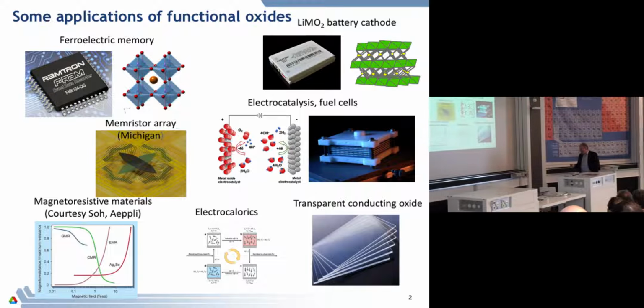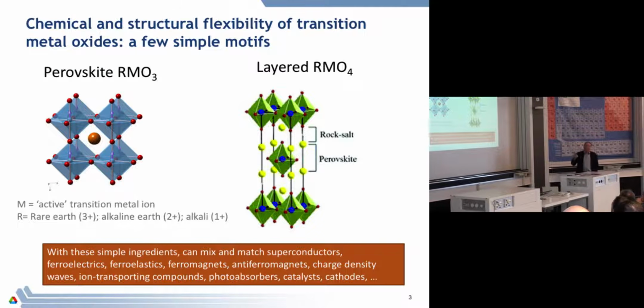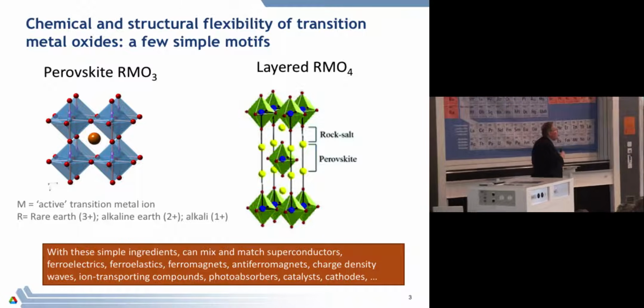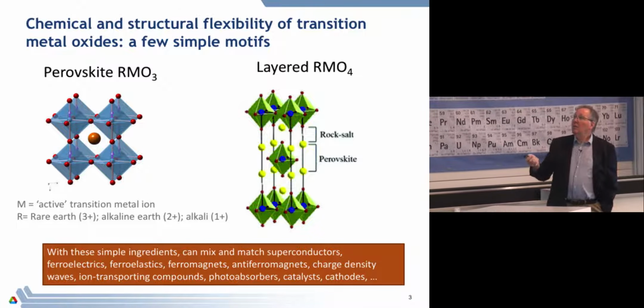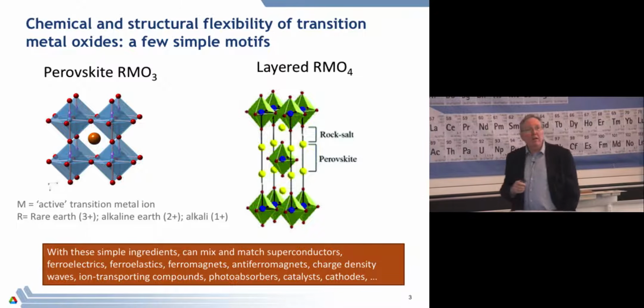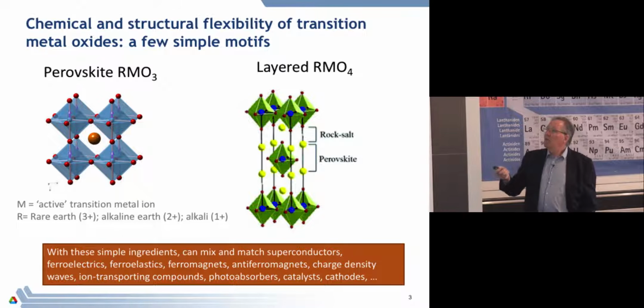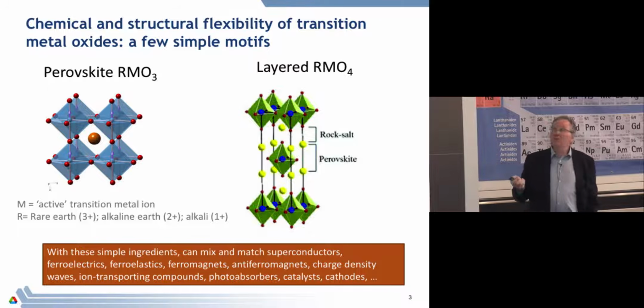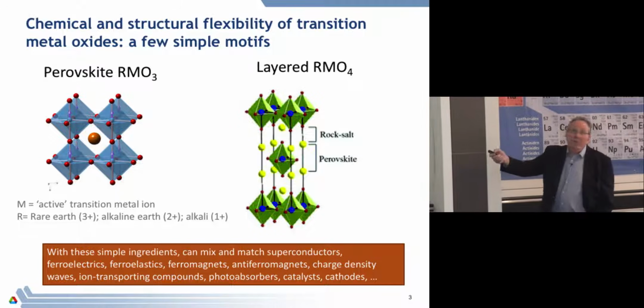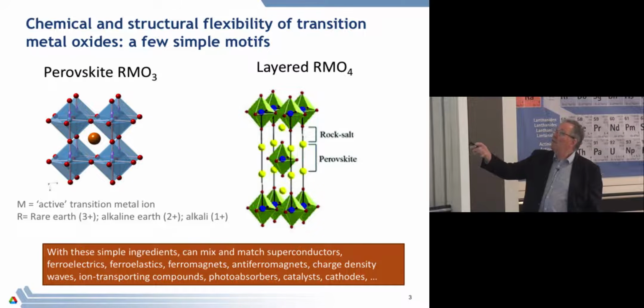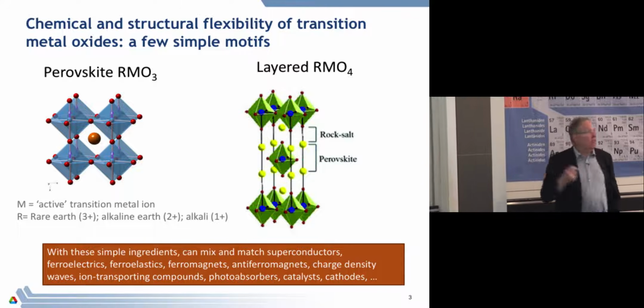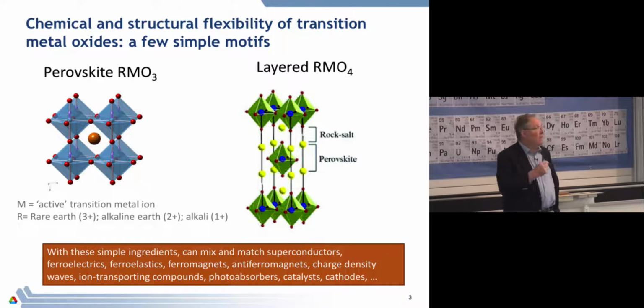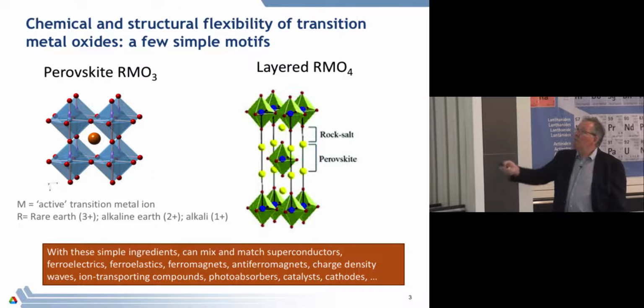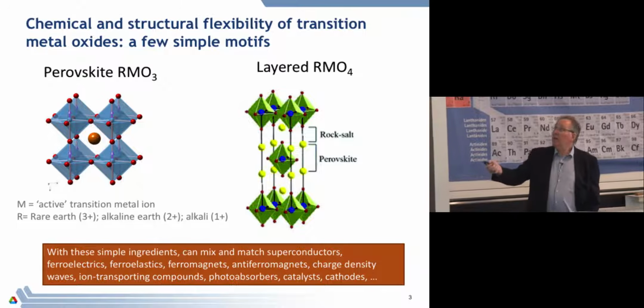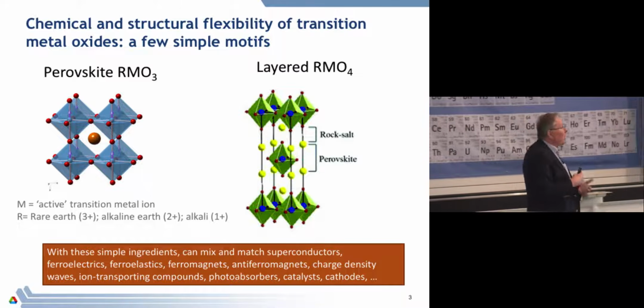And there are many others, but the basic physics that I want to talk about, and that is in most of those things, all comes from a flexibility of a few very simple ingredients of these transition metal oxides. And I won't get very complicated with structures. I'm going to talk almost entirely either about materials which are perovskite structures like this, or layered perovskite structures, but very similar to this. And in all of these materials, they have this kind of formula unit. So they're oxides. At the center of the octahedra is a transition metal atom. And that transition metal atom is the thing which is active. It may have a moment, so you can make magnets out of it. It may move off center so that you can make ferroelectrics out of it. It may change the shape of the octahedron so that you can make ferroelastics out of it.